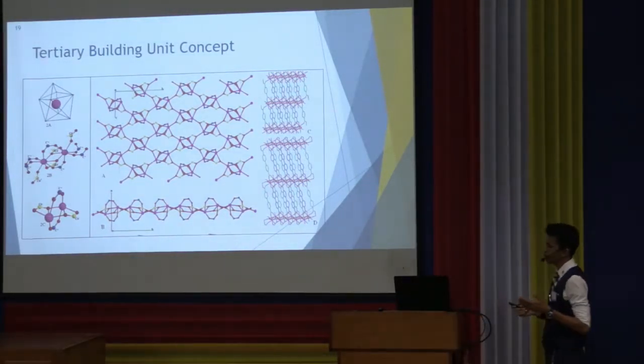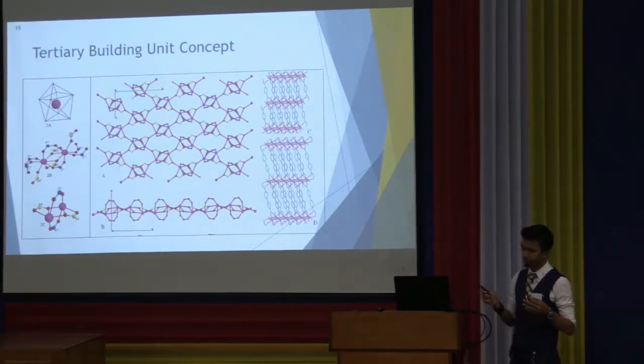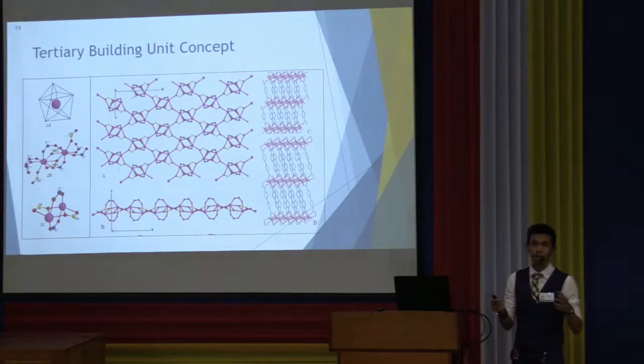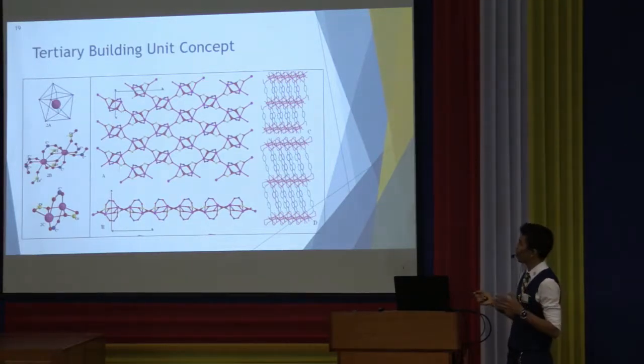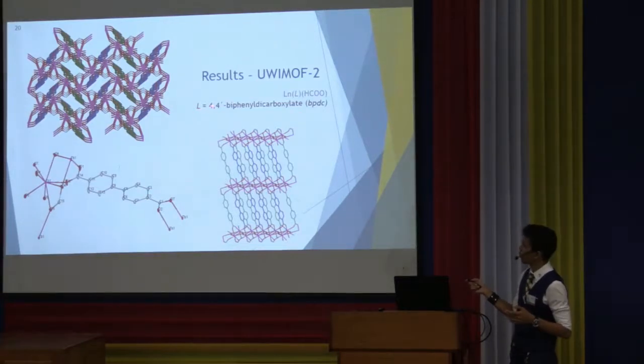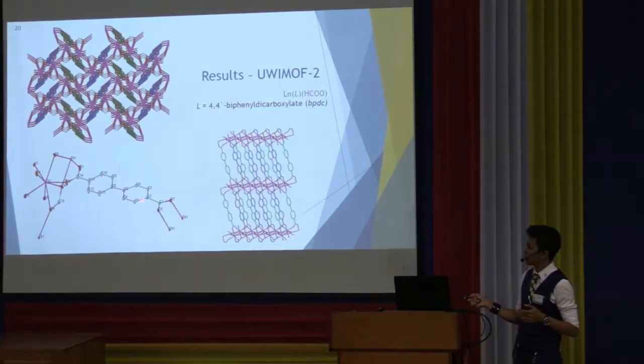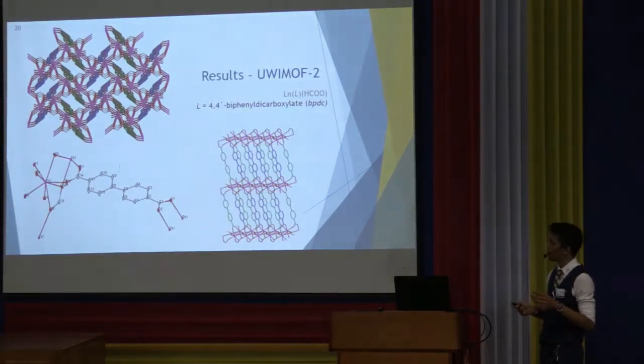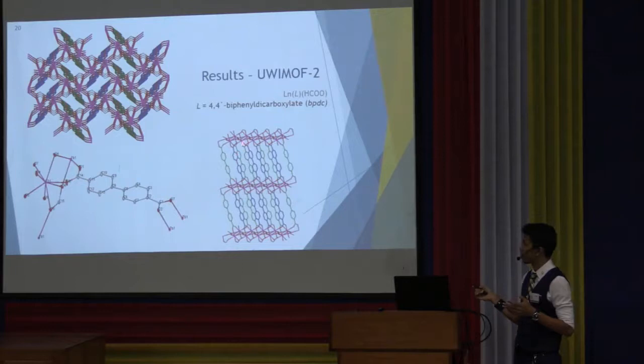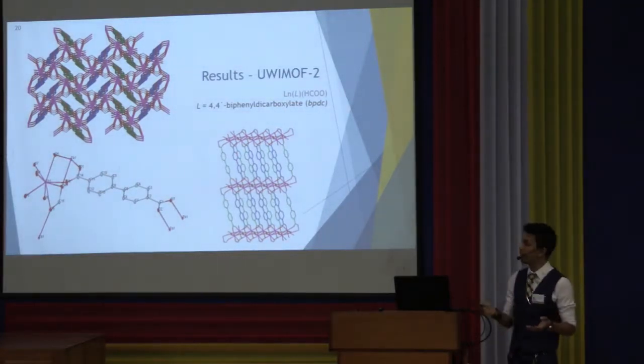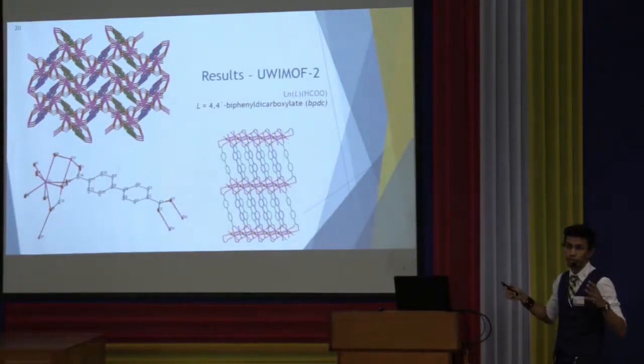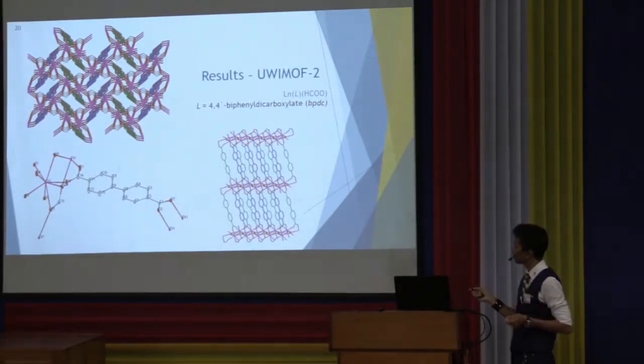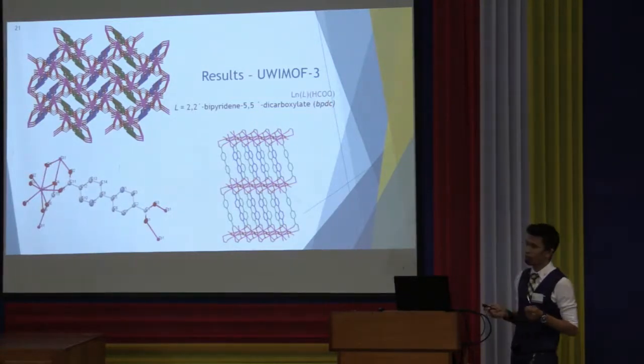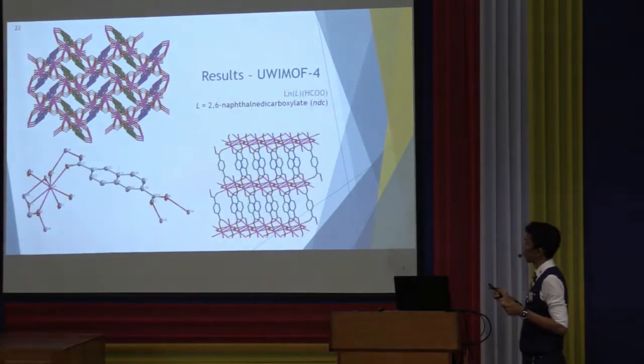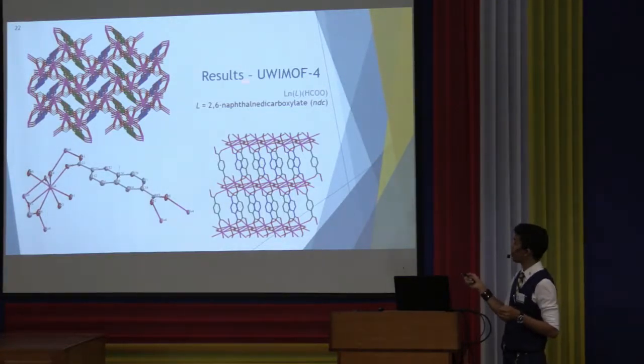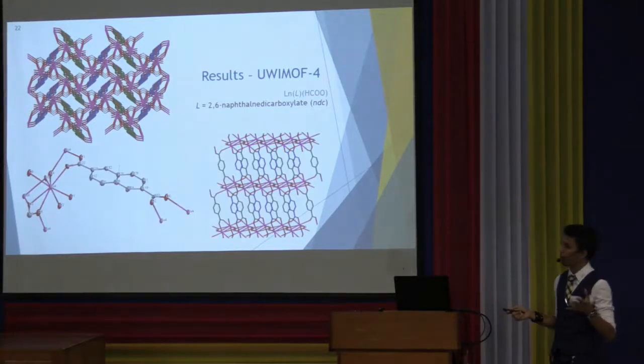In order to test this hypothesis, we designed experiments with similar but different linear ditopic ligands, and thus we got UWI-MOF2, which was made with biphenyl dicarboxylic acid linkers. Here it has 2 rings instead of the 1 in our first MOF, and we were happy to find that it was also isoreticular with the first 2 compounds, making this a third isoreticular member of the family. We were also able to do this with 2,2'-bipyridine-5,5'-dicarboxylate, as well as with 2,6-naphthalene dicarboxylate, making these UWI-MOF3 and MOF4, the 4th and 5th members of this isoreticular family.